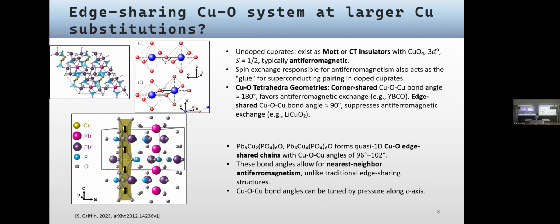Another consideration is that in a way, this copper-doped apatite system might share some similarities to the cuprate families, but not the cuprates of YBCO type. If you're talking about the geometry of copper-oxygen coordination, you see the YBCO type and the layered structures host so-called corner-shared geometry, which is presented here. But some systems, including quasi-one-dimensional systems, and as far as I remember, one of the specimens is the strontium-calcium cuprate, if I'm not wrong, have a so-called edge-sharing geometry, and it means different angles between copper and oxygen.